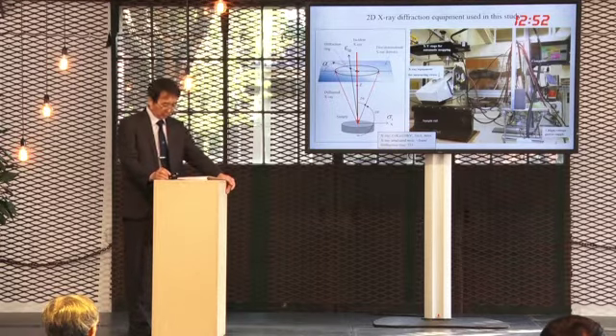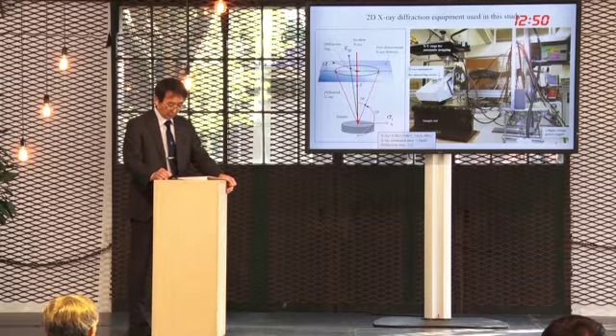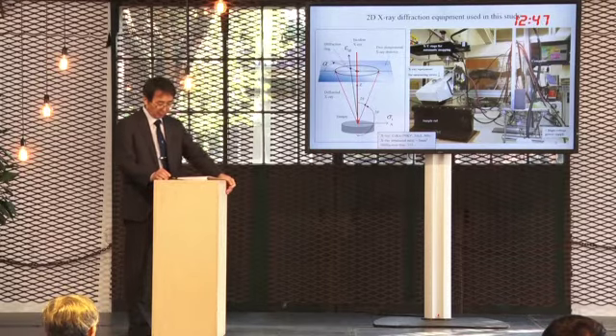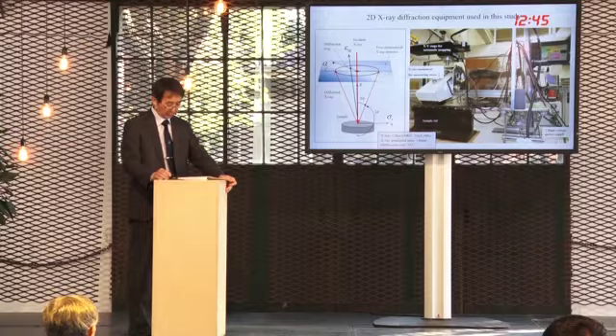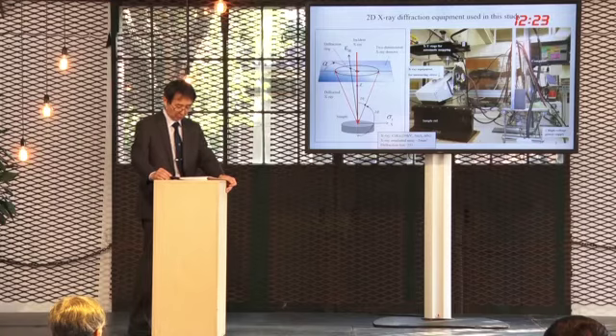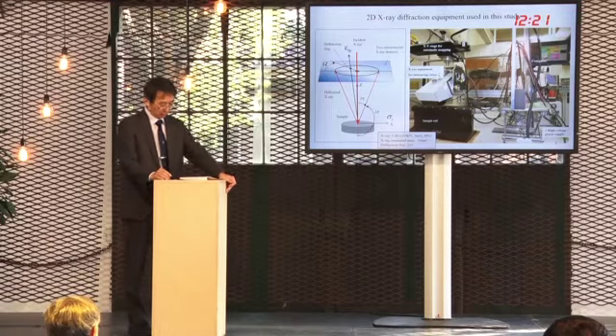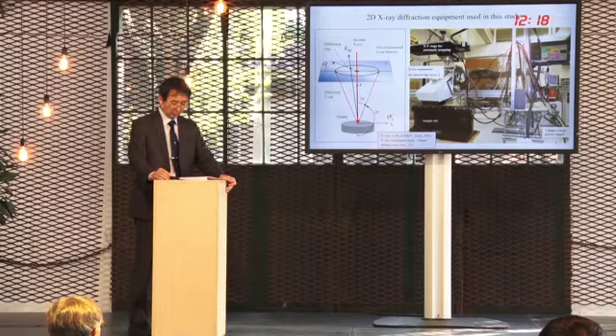The X-ray optics and equipment used in this study are shown in this slide. First, we measure the diffraction ring from the rail by using a two-dimensional X-ray detector, for which we used an image plate, IP. And next, we calculate the stress using strains obtained from the diffraction ring by using the so-called cosine alpha method. Details about the cosine alpha method will be explained later.